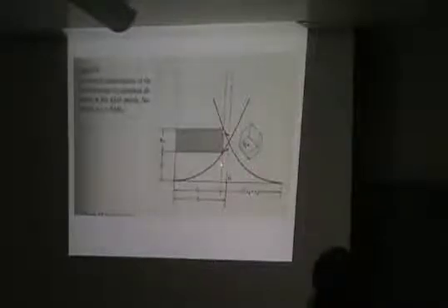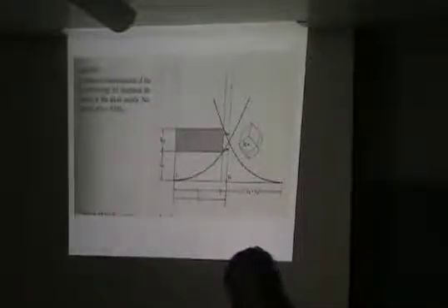Instead, you see at another characteristic frequency right here, you get this big bump, enhanced absorption. And again, that is happening because of interband transition in sodium as well. So here it is, sodium, the Fermi energy is here. This is the S band. The Fermi energy is here. So when the energy is less than this band gap, you're only exciting electrons or carriers around here. And that's the Drude part. And then when you make a transition across this, that's when you start to excite interband transitions. With me? Any questions?